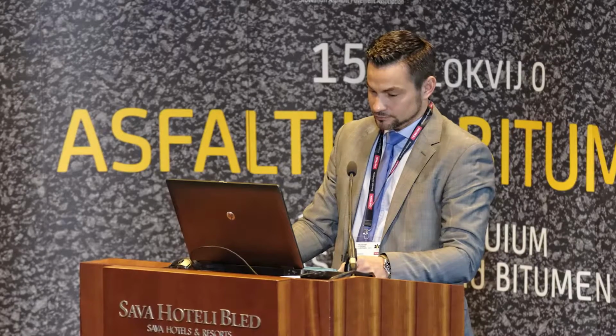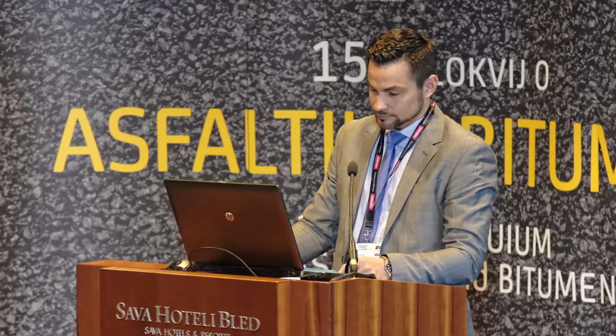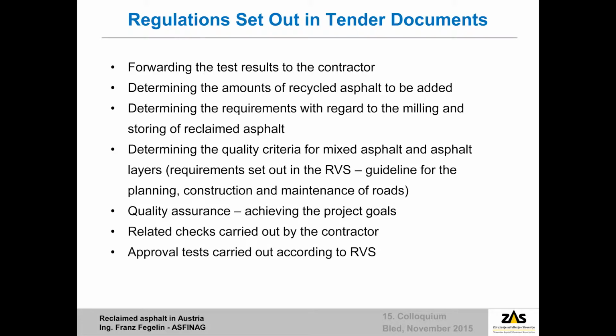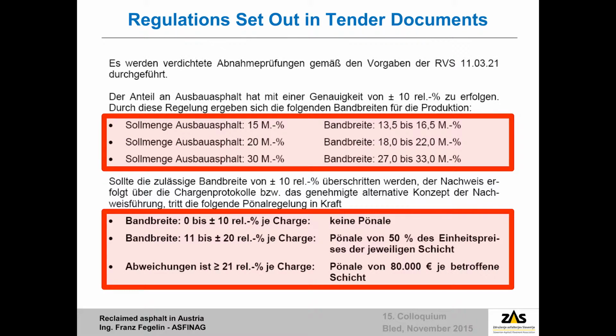Our next issue was which requirements and regulations were necessary for preparing our tender documents. First, all test results gained from the taking of sample cores were forwarded to the contractor, so it was possible to prepare the recipe for the asphalt mix and calculate the related costs. We regulate the amount of material to be reclaimed and the amount to be added, as well as the storage conditions. We fixed the project goals, the related checks, and set the quality criteria. Last but not least, we described the approval tests.